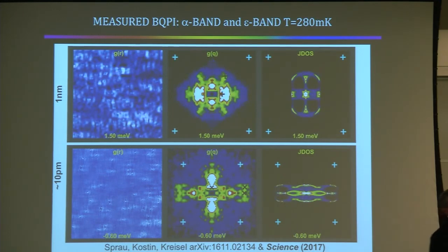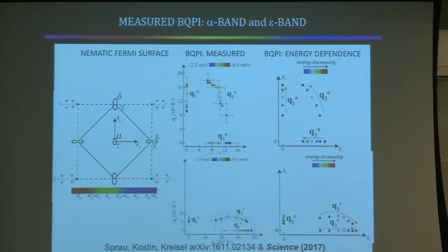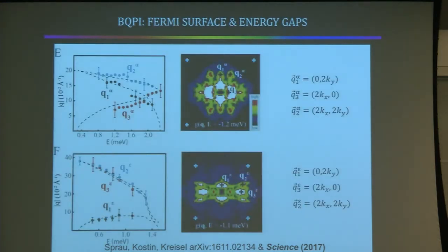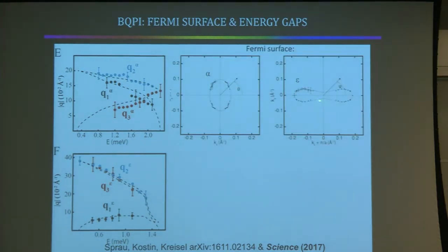So this is an arcane procedure, but what it allows us to do is to determine by measuring these Q vectors as a function of energy for 2 different bands, and then solving the geometrical equations telling us where the scattering interference was coming from in terms of where the quasi-particles are in momentum space, we can find the Fermi surface of those 2 bands. That's the first step. We make a high precision map of the Fermi surface of the 2 bands.